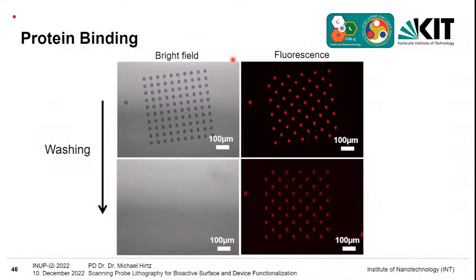We can also do protein binding again to show here. So here's another array spot, and if you look at it in fluorescence, you will see that only every second spot is visible in the fluorescent image. And this is because there are 2 different materials, though the color is the same. But in fluorescence, you can see that only here we have fluorescent material, and in between there was a biotin azide spot.